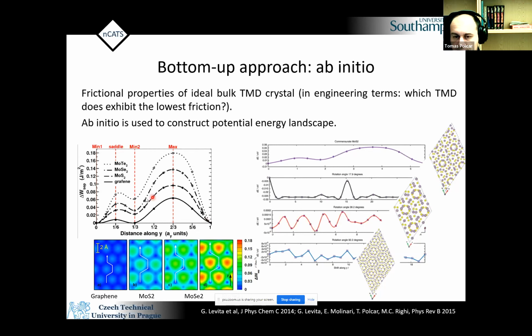And indeed, we did that, which you can imagine computationally is not an easy task, because then your cell gets really big. So we did a couple of tricks. We selected specific angles, and we calculated, again, the potential energy surface. And you see that you can get very complicated shapes, of course, instead of this commensurate one. What perhaps you cannot see are the numbers. These numbers are extremely small here. And it's what you expect, that basically friction of incommensurate surfaces will be much lower than the commensurate one. So this is one way to approach the problem from ab initio.